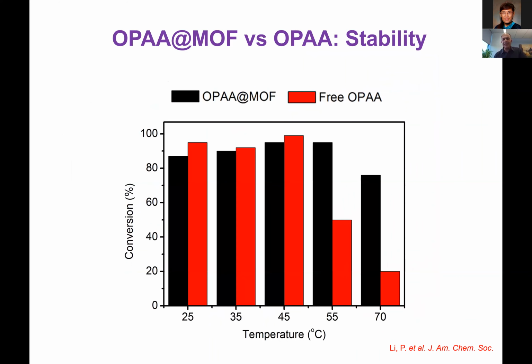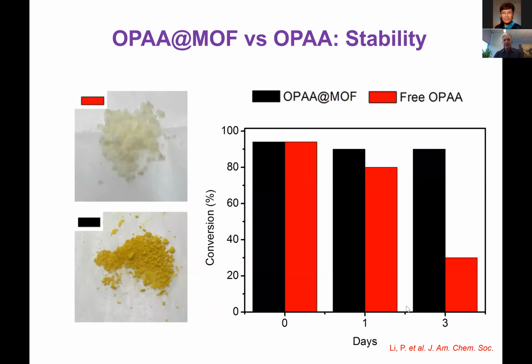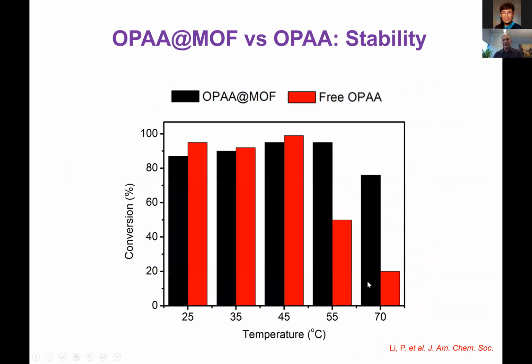But how about the stability? The DOD wants to know, are these enzymes stable at high temperature? So here we take the enzyme at different temperature, we soak it for 20 minutes, 30 minutes, then we do the catalysis. And what do you see? Actually, after a while, the free enzymes start to die drastically versus the composite is doing much better.